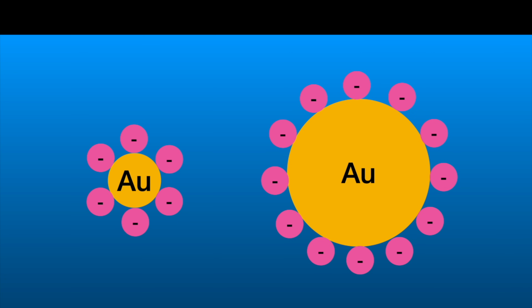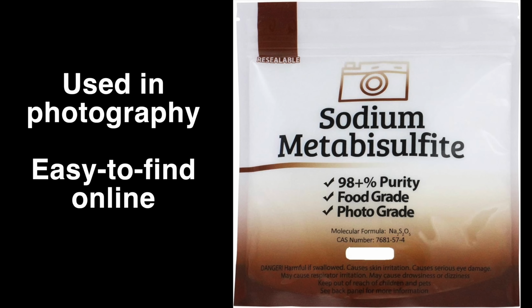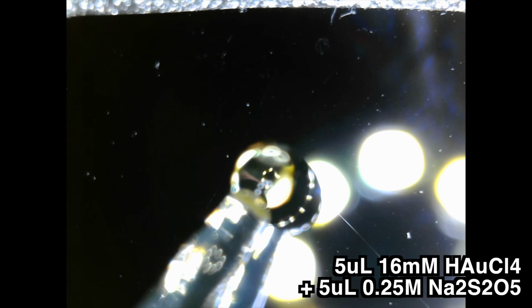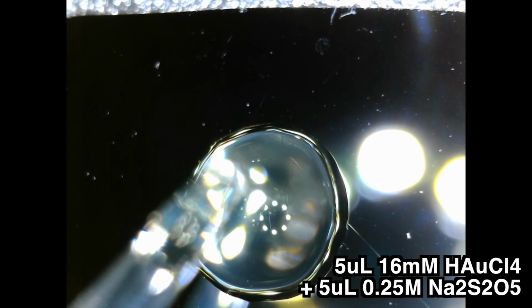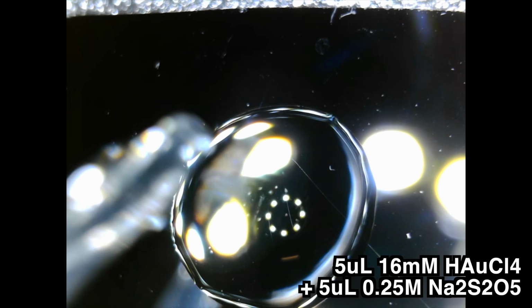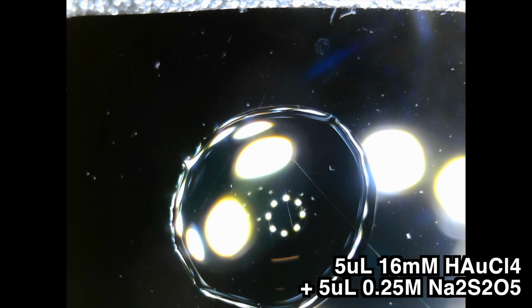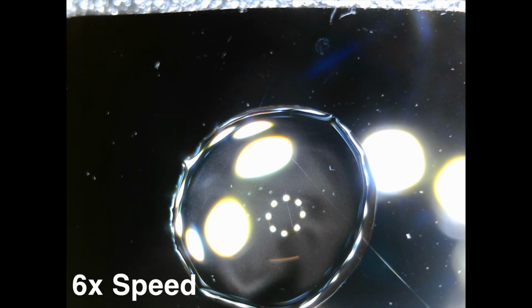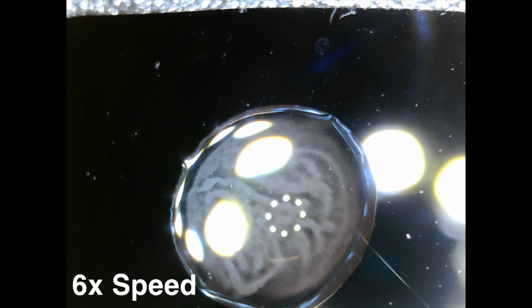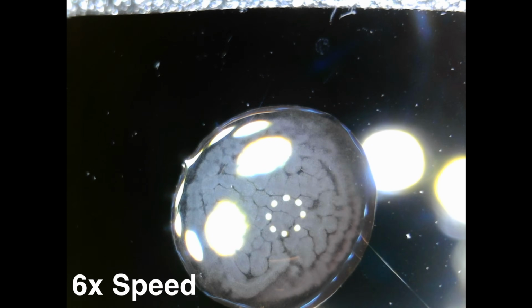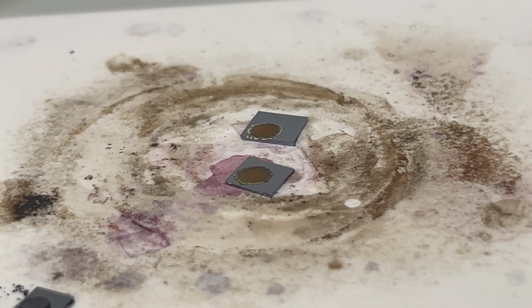In addition, because we are no longer relying on the citrate to stabilize the particles in solution, we are free to use a different reducing agent. I actually found that sodium metabisulfite worked well for this. I got a new chip and applied about 5 microliters of chloroauric acid. And then to that, I added 5 microliters of the sodium metabisulfite solution. After a few seconds, the drop became cloudy as gold particles began to be produced and settled out onto the surface. I dried the chip and put it into the SEM for imaging.